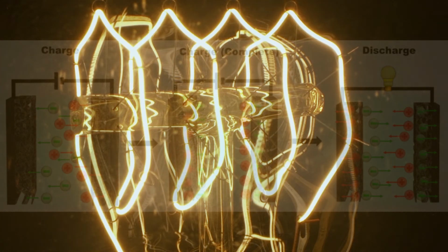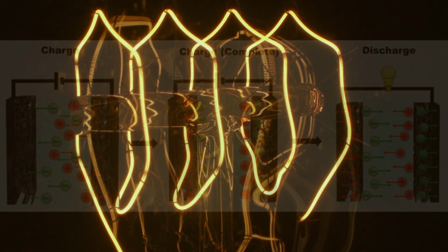The areal capacitance of the PEDOT:PSS polymer, ferritin, multi-walled CNT-based fiber supercapacitor in a phosphate buffer saline solution was 33 millifarad per 1 square centimeter, with an areal energy density of 0.82 microwatt-hour per 1 square centimeter. This showed an increase over the guest-free multi-walled CNT yarn, yielding values 52 times greater than the latter. Within the mouse, the supercapacitor exhibited biocompatibility and successful operation, seeing as how the capacitance maintained above 90% after 8 days in vivo.